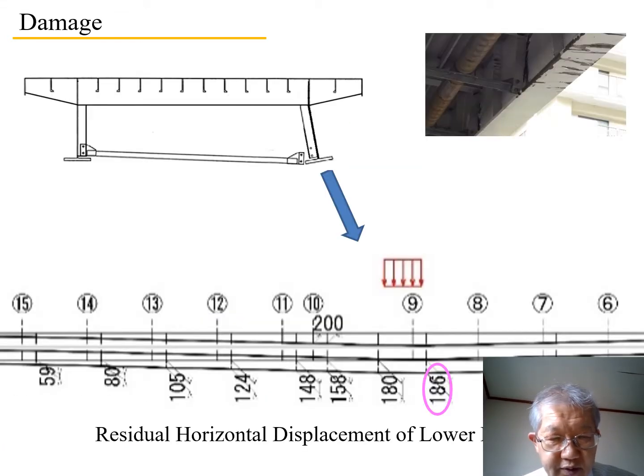So after the owner found out the problem, the residual horizontal displacement of the lower flange was measured, and this is the result. The maximum displacement was found around section 9, which is 186 millimeters. We also observed around here the bottom surface of the lower flange somehow scratched, and there was removal of coating around here. So we have concluded that the collision occurred around here.